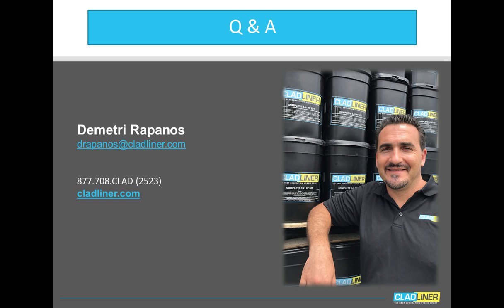Cladliner can be applied on the bottom when it's wet. The only concern would be if we have water running through the channel, we can stay out of the channel. If we need to line the channel, the flow, if there is any flow, would have to be stopped before that area got lined, and the product would have to reach some form of cure before the channel was released